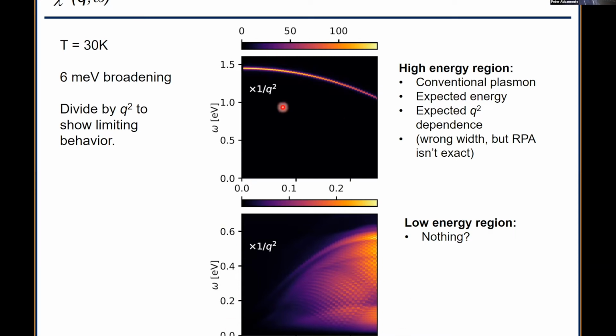So this, by the way, is a color map. This is momentum on the horizontal axis, frequency on the vertical. The color scale is the imaginary part of chi, and chi goes like q squared for a conventional plasmon. So what's plotted here is chi double prime times 1 over q squared. So you can see the intensity goes to a constant here, which means that the sum rule is also being satisfied. If you look at low frequency, actually, well, nothing jumps out at you. You don't really see anything there.